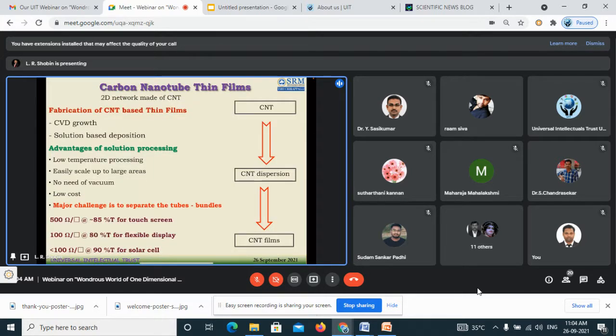So how are we going to fabricate such a transparent film using this black powder, carbon nanotube? So first you should have a carbon nanotube. You should have a clean material or a purified carbon nanotube, which can be obtained using CVD growth or a solution-based method. You can deposit a film.